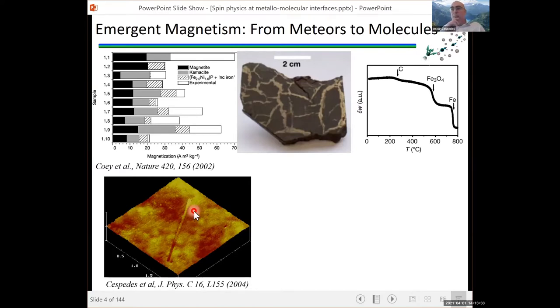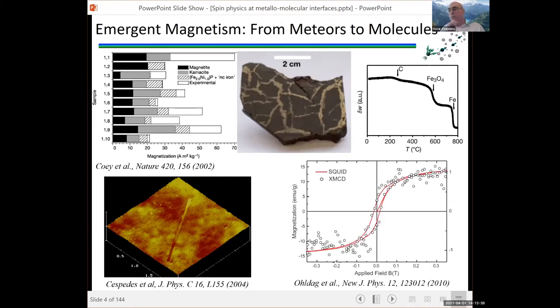The other interesting paper to me from this area was from the group of Pablo Esquinazi, who published a lot of results on magnetic carbon. But in particular, he did some work together with the BLS, the Berkeley Light Source, where they irradiated graphite with hydrogen, and they did some extensive measurements, including SQUID measurements. And they could demonstrate by taking PEEM images and XMCD measurements that the areas of graphite irradiated with hydrogen did show magnetic contrast and were responsible for the magnetic hysteresis loop that they could see in the sample. It wasn't just that they had impurities.